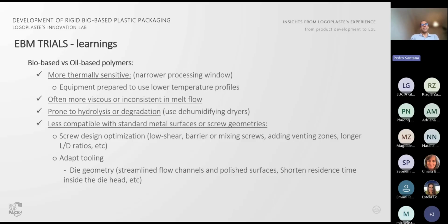In other words, after the initial trials and processing attempts with the materials developed in the project, it was concluded that these materials are extremely sensitive to temperature profiles, displaying a very narrow processing window. Even small temperature increases lead to rapid material degradation, making it either overly fluid or brittle. This instability compromises the process consistency and highlights the limited compatibility of these materials with the current industrial equipment and tooling, which are designed for conventional oil-based materials.